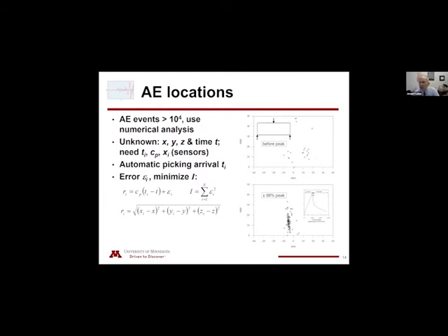So I'm just showing the XY coordinates of these events prior to peak load up to about 98% of peak load. And I would argue that these events are more or less random, that I cannot readily identify where the crack will start developing. If we now remove these events, and I should say these events are located with an error less than 2 millimeters. So these are good locations. I now remove these events and I show events only in the region right around peak load.